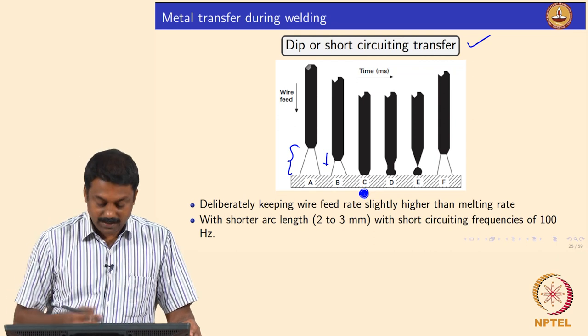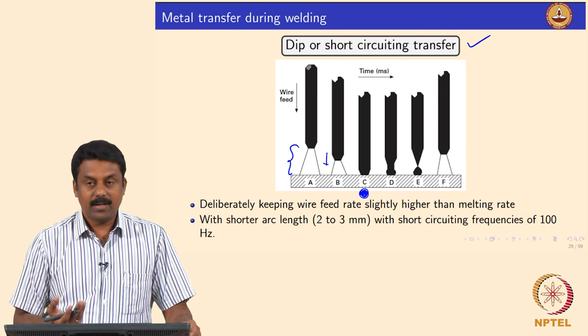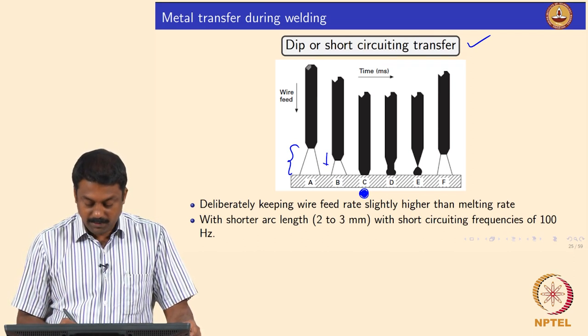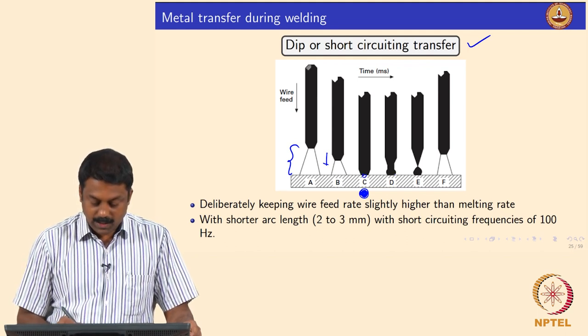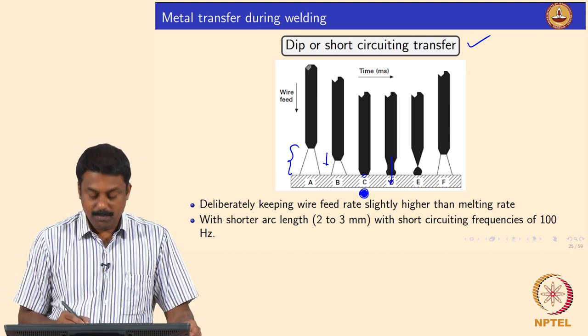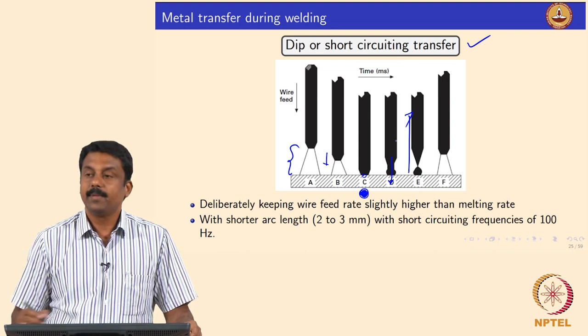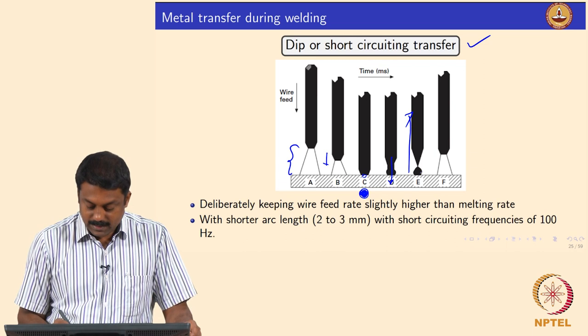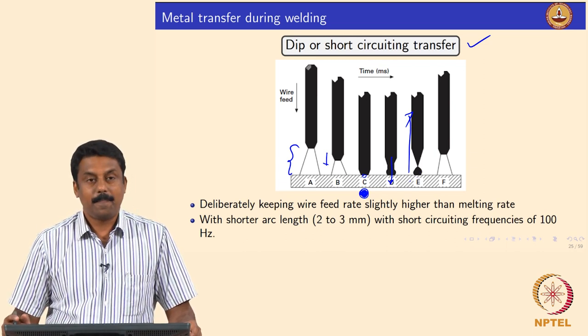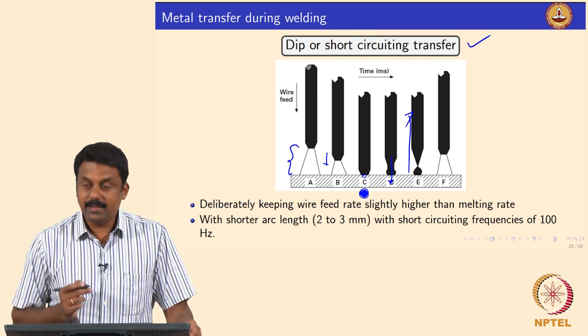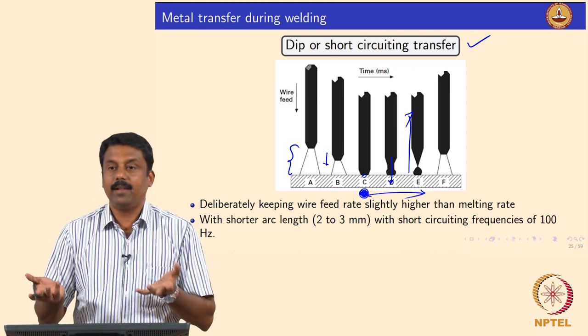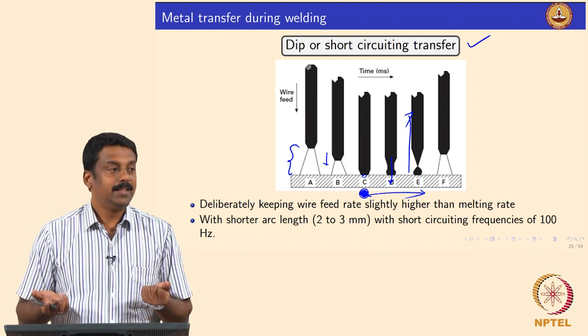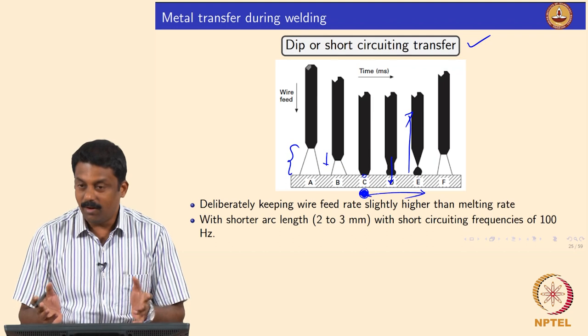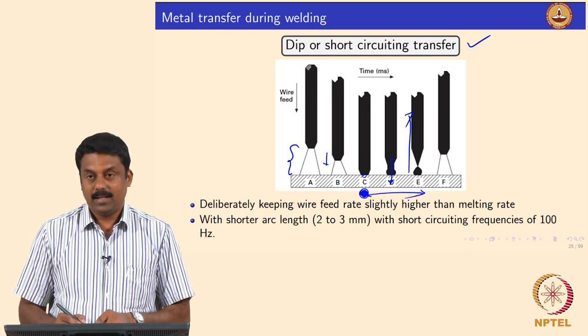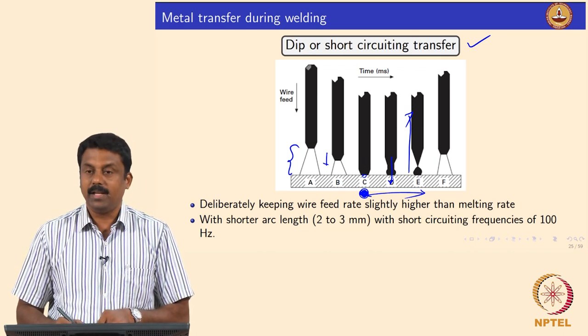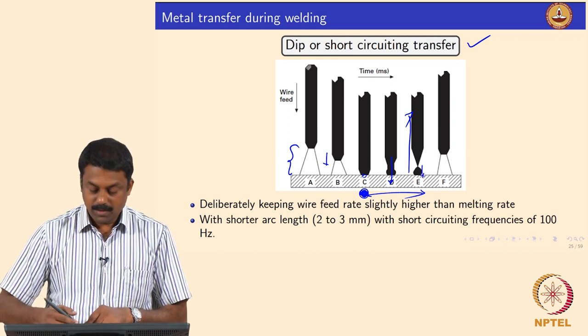And then what happens? Once the short circuiting happens, you can transfer the droplet to the workpiece. So, you form a droplet, and then once you are dipping it, you melt the droplet, and subsequently you can pull the wire back. Whatever is molten is detached by the surface tension of the weld pool. Yes, it is clear. In this process, the advantage is that during these three steps, the arc is not there. The moment the short circuiting happens, the arc is gone, and then you can dip the filler. Either the filler can melt before the short circuiting or during short circuiting, and then you can transfer the droplet by retracting the wire back.